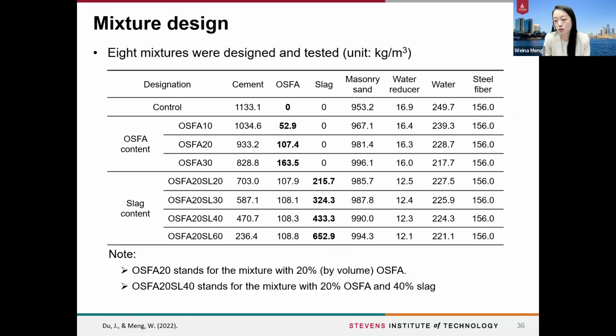So in our studies, we investigated three groups of UHPC with different binder systems. The first one is a control, so we have 100% cement. The second one is a binary system. We have the OSFA with different content and the cement. And the third group is 20% fixed OSFA, sorry, OSFA with different content of slag and cement.